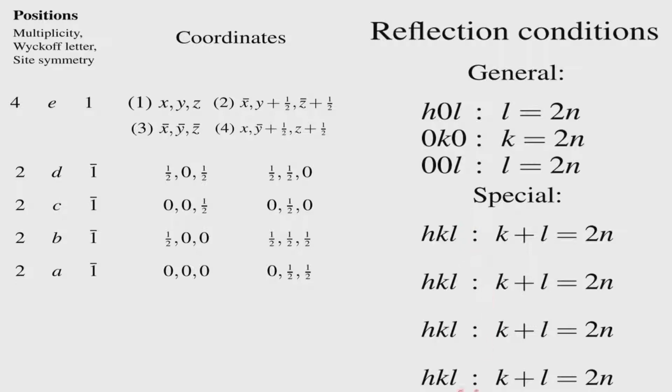So, all the general reflections will show the presence of the 1 bar symmetry that is associated with P 2 1 by C. So, if there is a molecule with a special symmetry which is occupying this particular space group, you will have these additional special condition symmetry absences. It looks as though the general reflections have an absence, which would mean it has to be centered. It is not necessarily that it has to be centered. This indicates the A centering, but it is not really A centering. It is a consequence of the atoms sitting in special positions.